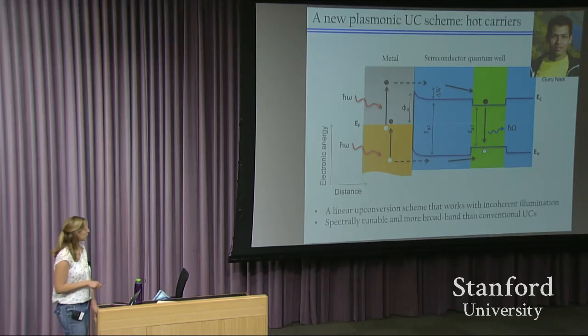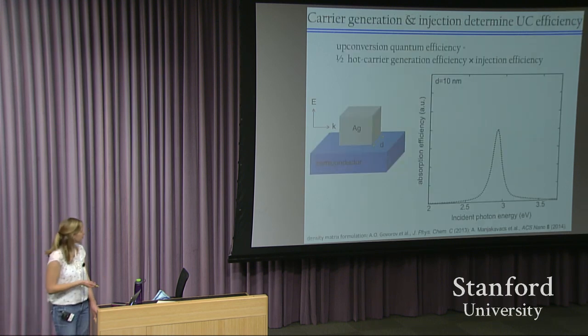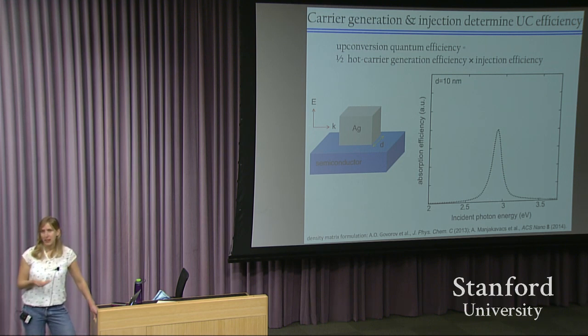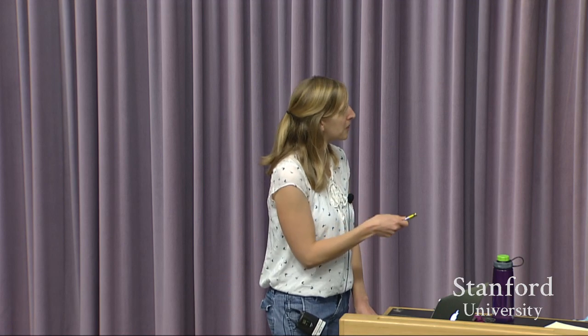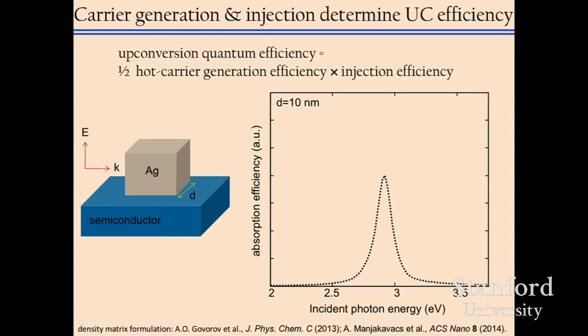And it's also spectrally tunable and more broadband, based on how you nanostructure this metal. So let me just quickly talk you through some calculations. If you take, for example, a metallic nanoparticle on a semiconducting substrate, the absorption efficiency of this nanoparticle tends to peak at a given energy. That energy can be shifted around just based on the metallic material you're using and the size of the particle. So here, this is something called the plasmon resonance, where the particle is absorbing most strongly.